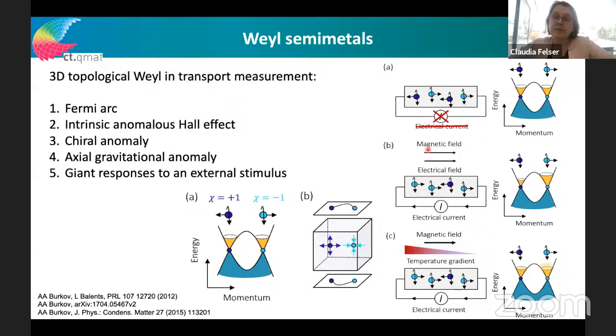And instead of an electric field gradient, we can also apply a temperature gradient. We like to measure thermoelectric properties of the material too. We would see a related effect, the so-called axial gravitational anomaly, which was predicted by Subir Sachdev and others, and was already also investigated in bismuth. I think Jörg Herrmanns already reported about this, even at room temperature, in antimony-doped bismuth Weyl semimetal, so you may have heard it before.